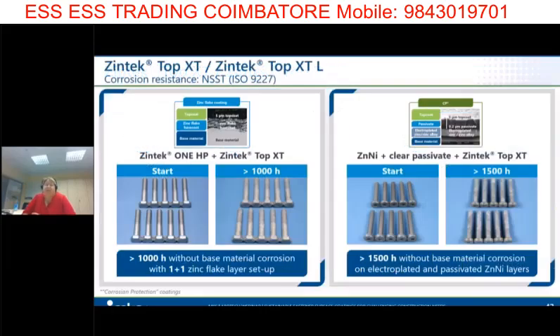Here on this slide, the really nice corrosion results you can achieve with it. On the left side, the combination in the zinc flake world, so having Zintek 1HP plus Zintek Top XT, and with just this 1+1 layer solution, you can achieve up to 1000 hours without any red corrosion. By using it in combination with a CP solution, so having the Zintek Top XT on a passivated zinc nickel layer, for example, you can achieve above 1500 hours without any red corrosion. So really a nice increase of corrosion resistance you can achieve by using the Zintek Top XTL.